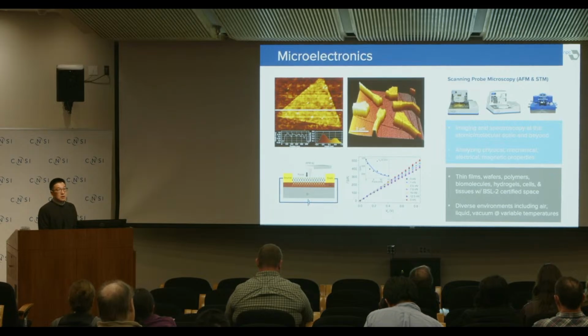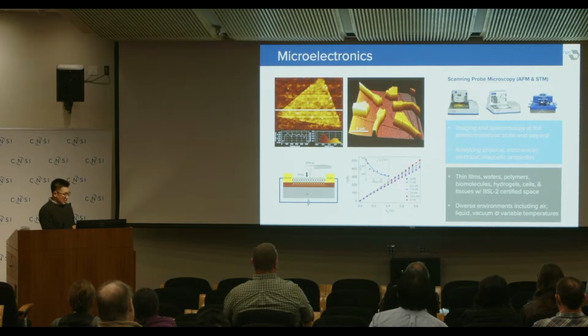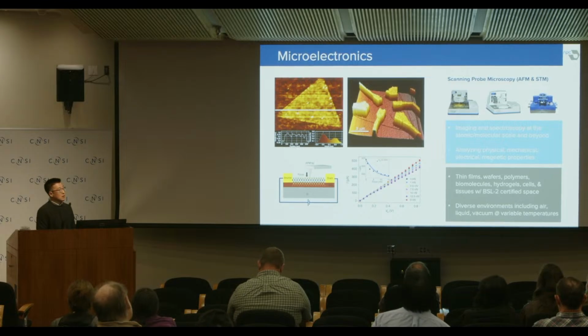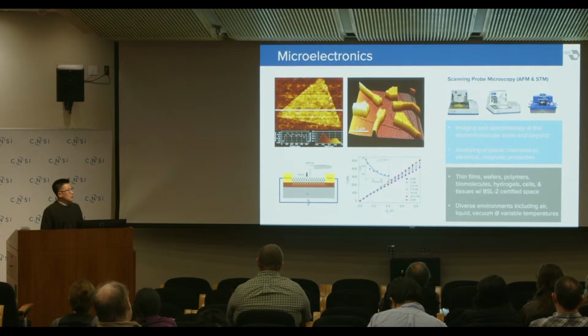And not only that, we can also create 3D images by using these AFMs. On top of this, another advantage of this AFM is we can analyze different types of characteristics, such as the mechanical or electrical magnetic property. In this case, it's piezoelectricity. So by using this AFM, you can obtain the IV curve with applying different amounts of force. So you can see the IV curve is shifting. The slope is different depending on the force we are applying on the surface. So based on this application, we can measure the different electricity, which is piezoelectricity, the property using these AFMs.